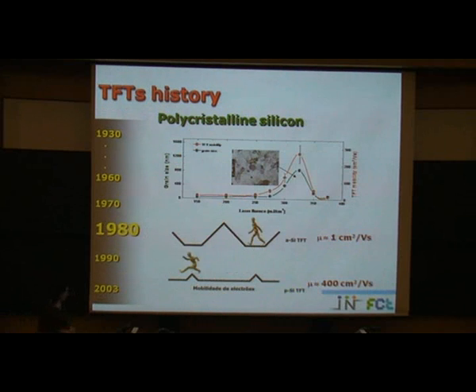In order to improve the performance of this type of TFTs, one of the ideas that appeared around the 80s was to crystallize amorphous silicon. For example, if you use a laser, we can increase the grain size. In this graphic, the green dots are the grain size, and the orange curve is the TFT mobility. As the grain size increases, we also observe an increase in the TFT mobility, and we can achieve values around 400 square centimeters per volt per second. So we can increase a lot the mobility of the device, or the electrical performance of the TFTs.